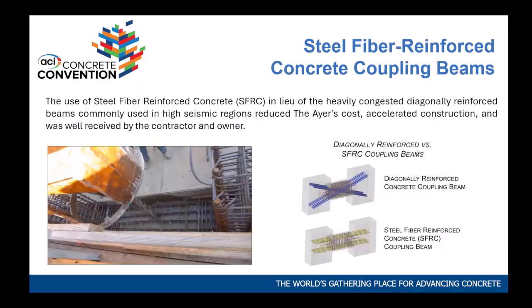So that was a big thing on constructability and buildability. The other cool thing on that job is we used actually fibers link beam. High dosage of fiber, you could see it, and instead of using the diagonal reinforcement in these beams because they are taxed by a lot of shear, and a regular beam does not work. So what we did here, we put basically that piece of concrete between the two walls. So this is a boundary element of the wall, and this is the other boundary. Between the two walls, we put a special mix with high fibers.